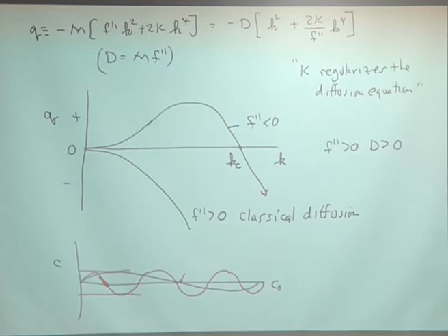Basically, it makes it now a well-posed evolution equation rather than this thing that blows up at sufficiently small wavelengths. Okay? There are some other important things here. If you look at this, there's a wave number with the maximum growth rate. We can define Kc as where Q at Kc equals 0. Km is defined as where the derivative of Q with respect to K equals 0. This is the wave number with the maximum growth rate.